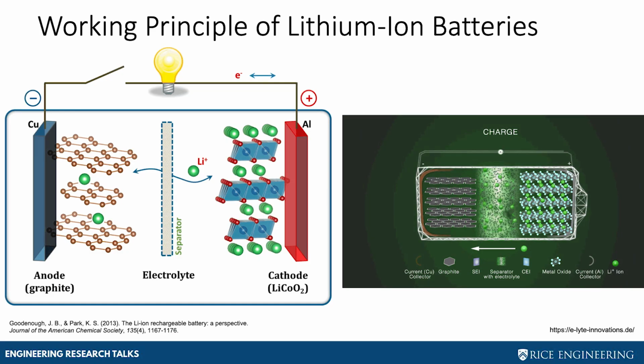So let's take a look at how lithium-ion batteries operate. There are some key components to think about. There's the active materials. We have an anode, we have a cathode. Separating that is some type of polymer separator. And we have some type of electrolyte that carries and conducts our ions. Lithium will actually transport and shuttle through. Usually it's going to be when you're charging, it's moving from our cathode material to our anode material. And you start to see that there's first this very slow movement of these ions, and then it goes through some resistance through the separator, and then it intercalates into our anode, the most common one being graphite. There's lots of changes that are happening. There's lots of chemical reactions that are happening at these interfaces. Once we've charged it as much as we can, we go ahead and reverse the cycle, and that's the discharge. And we do this over and over again for hundreds, hopefully even thousands of cycles on here.